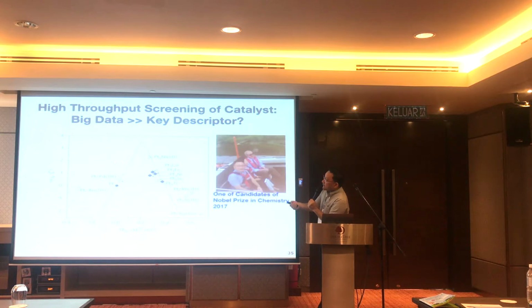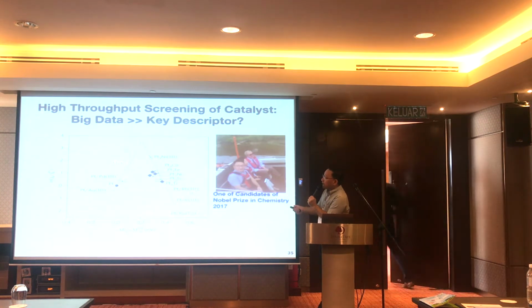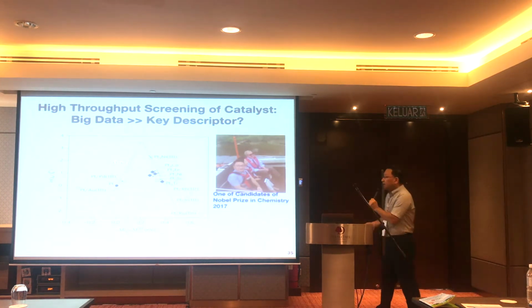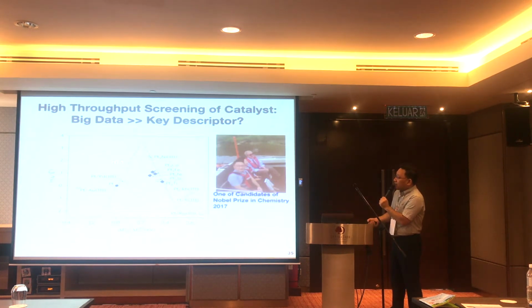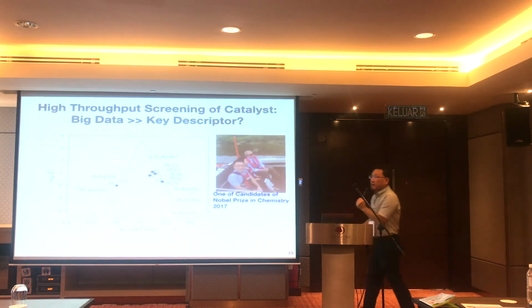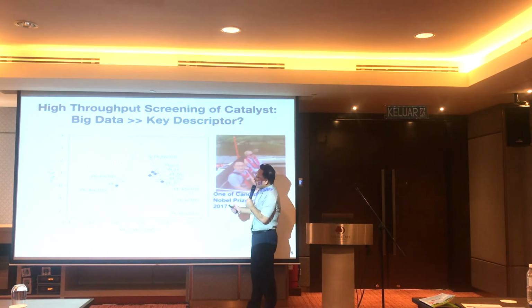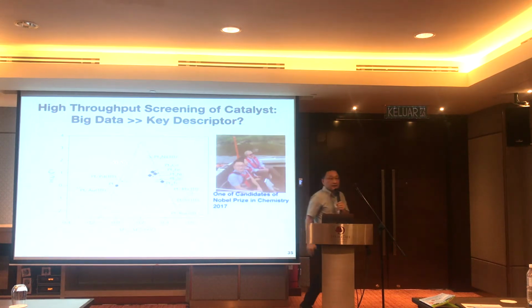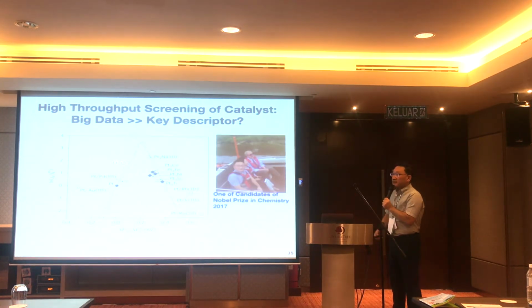Okay, there are catalyst activities. From experimental measurements, there are many different materials with experimentally measured activities. Can we find very strong candidate descriptors which can describe these material activities? He found that experimentally you can measure oxygen adsorption energy on these different materials. Then it gives you the activity predictions. This is a volcano curve, right? So many people try to design different materials located near the top of the volcano. Believe it or not, all of those materials are published in Nature and Science.